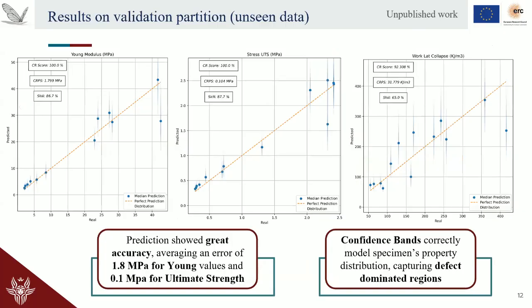So here are the predictions, for example, for the rigidity, the UTS strength, and the energy absorption of the metamaterials. And as you can see, the predictions are good. We are talking about 1.8 megapascal of mean absolute error for Young's modulus and 0.1 megapascal for ultimate tensile strength. But what is nice is that those results aren't just scatter plots, they also present a confidence region, which is just a one-dimensional projection of a 2D statistical distribution. And that's very nice because it allows you to do some statistical consideration about what you are seeing. For example, the lower bound, upper bound, confidence region, whatever you like. So it's very useful for engineering purposes.